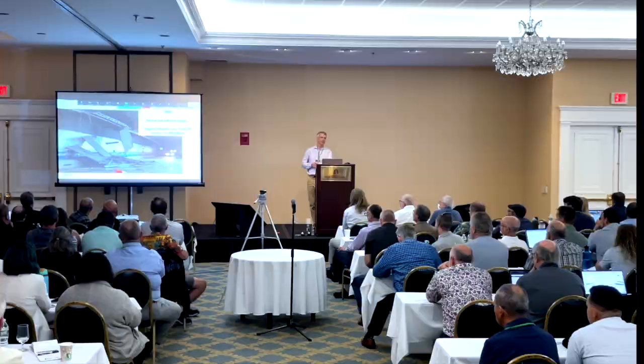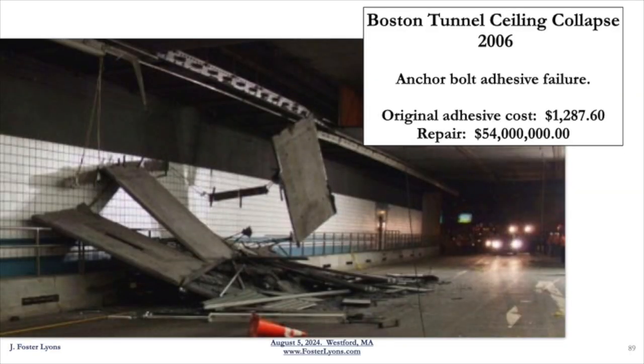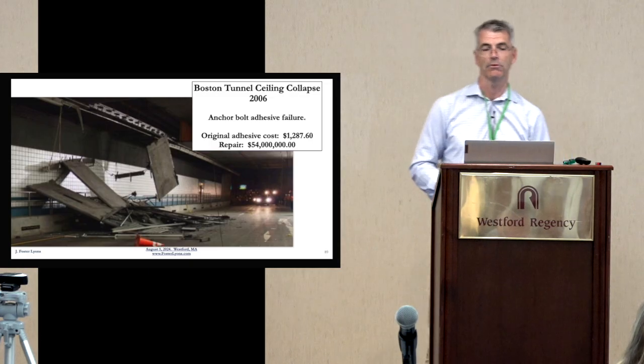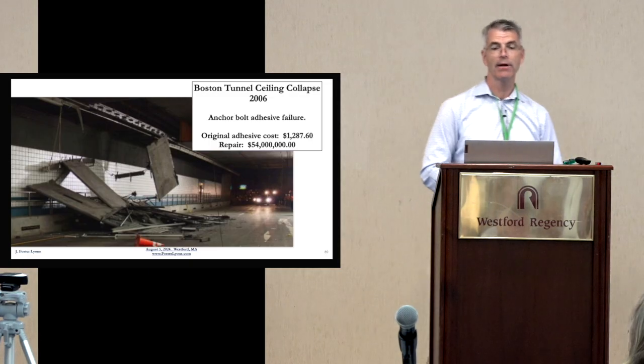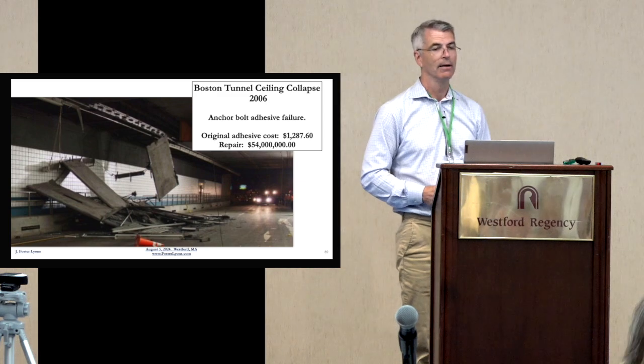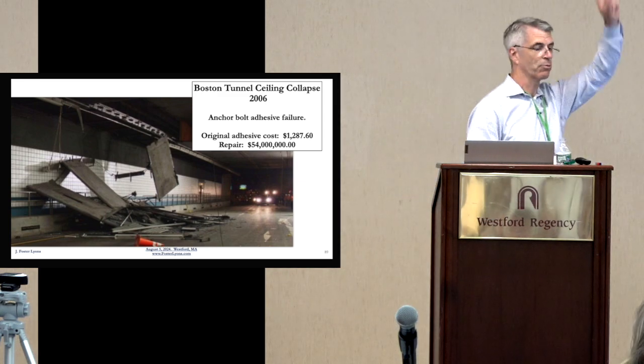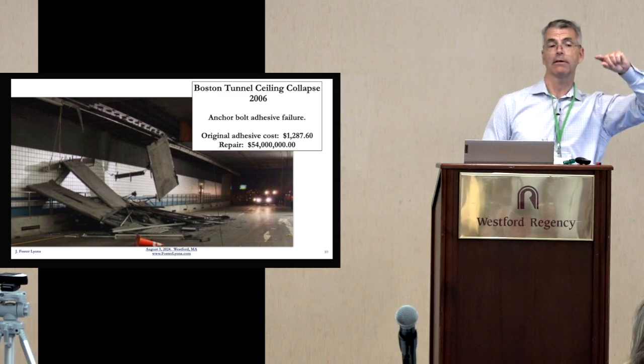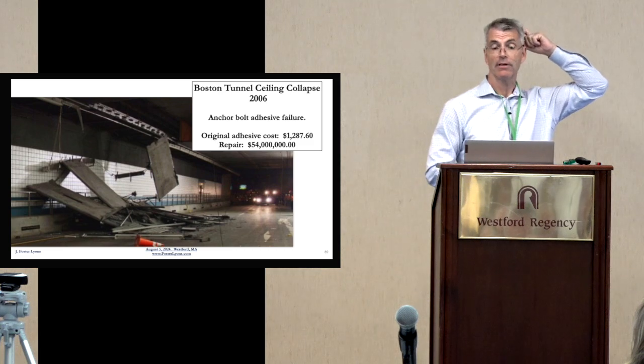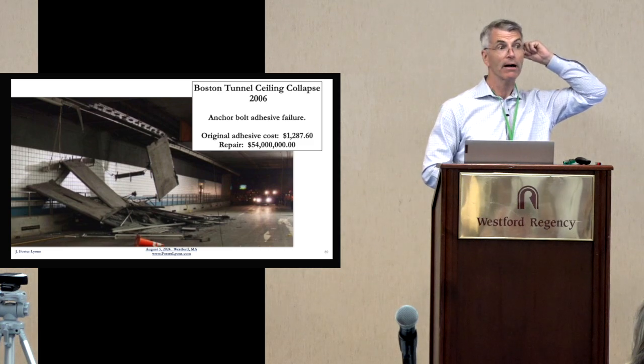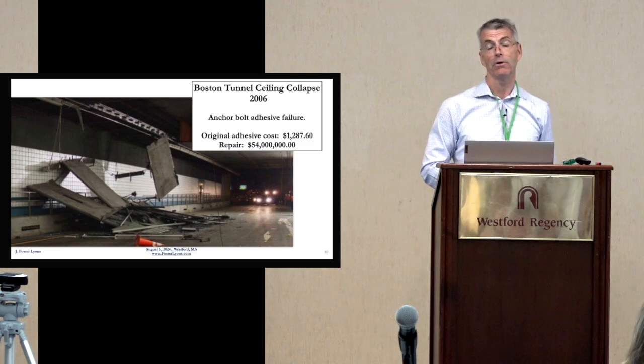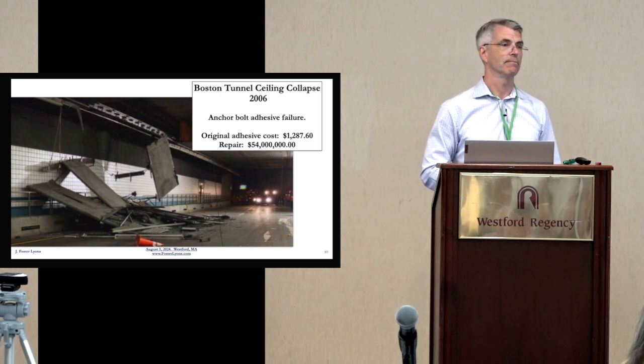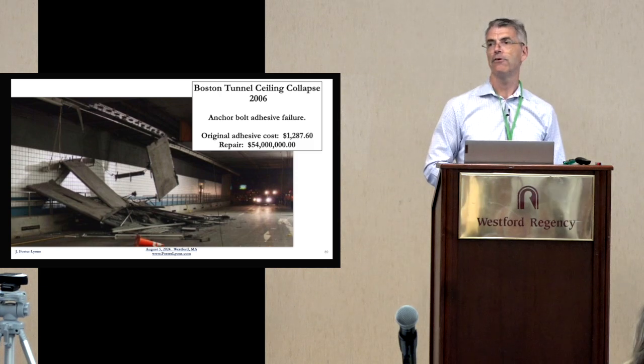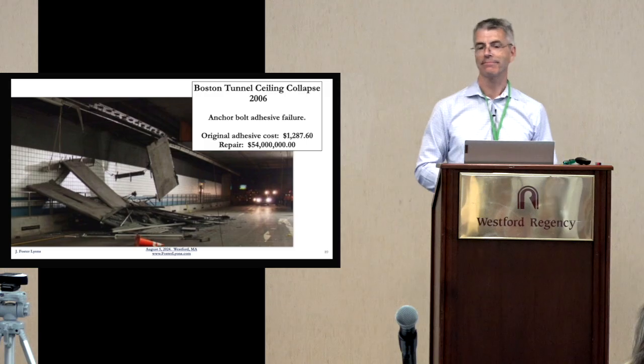Skip that one. So this is the Boston Tunnel. The ceiling collapsed in 2006. Unfortunately, somebody was killed in the collapse. But this was an anchor bolt adhesive failure, okay? And these bolts were drilled and set into the concrete ceiling with epoxy adhesive. The total cost of the epoxy in the tunnel was $1,287.60. The repair was $54 million. Oops.